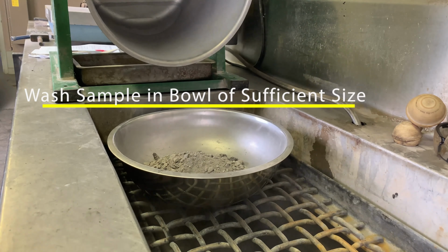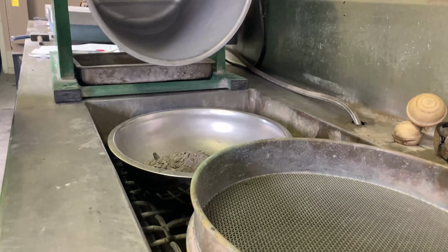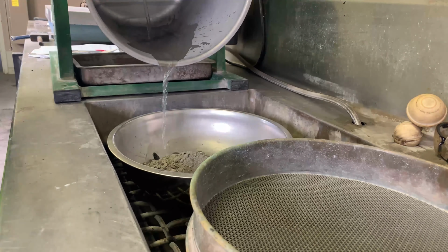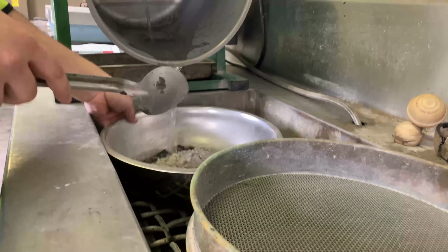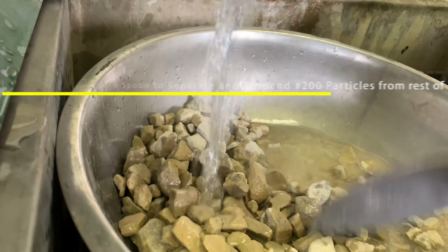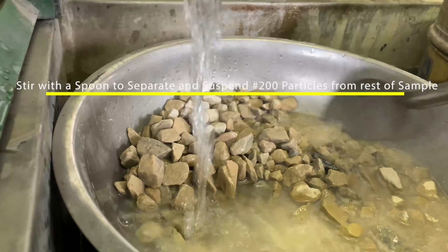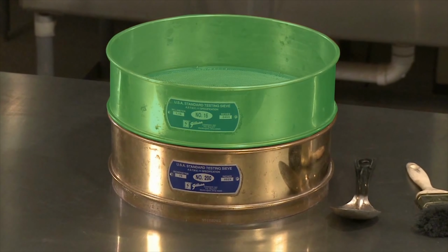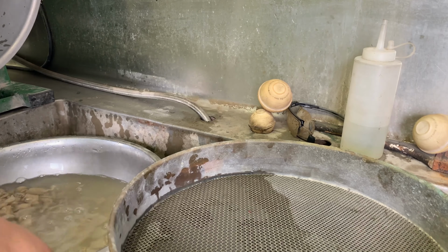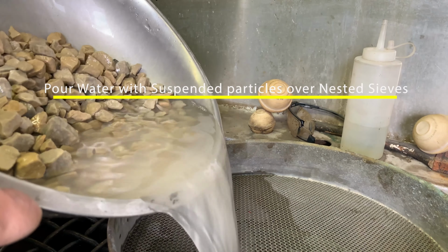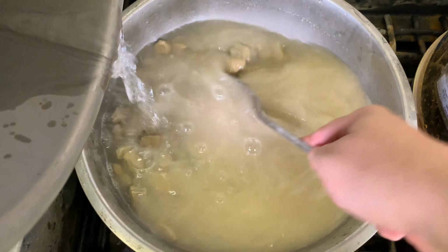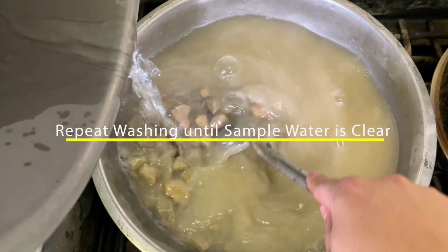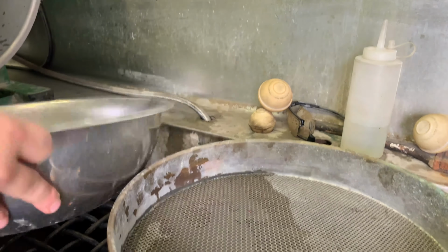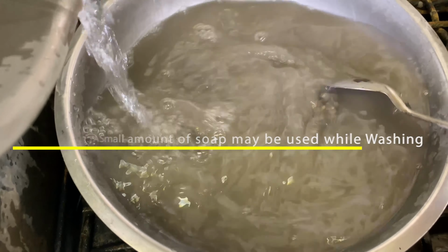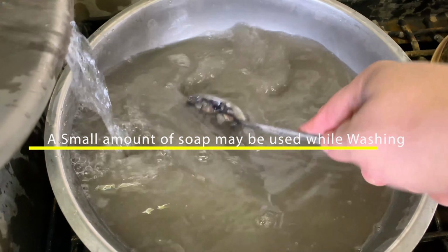Wash the sample in a bowl of sufficient size. Stir the sample with a spoon to separate and suspend the number 200 particles from the test sample. A number 16 sieve is nested atop a number 200 sieve. Pour the water with suspended particles over the nested sieves. Repeat this washing process until the sample water is clear. A small amount of soap may be used while washing the sample.